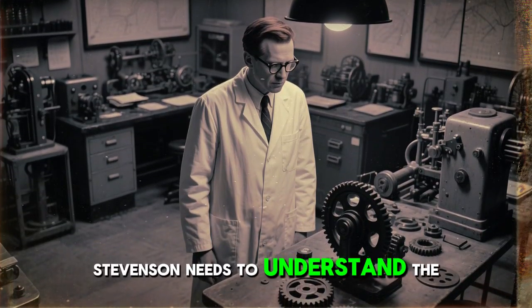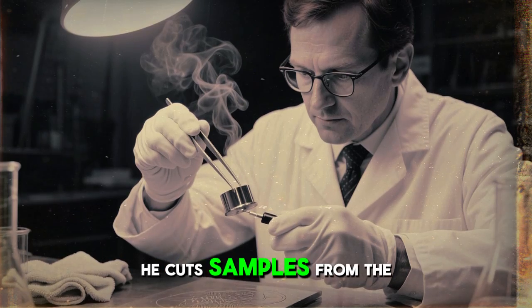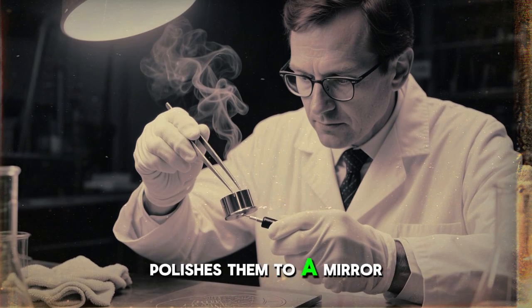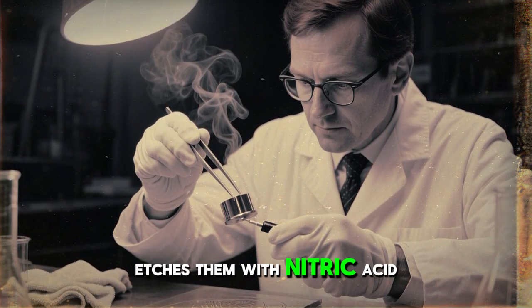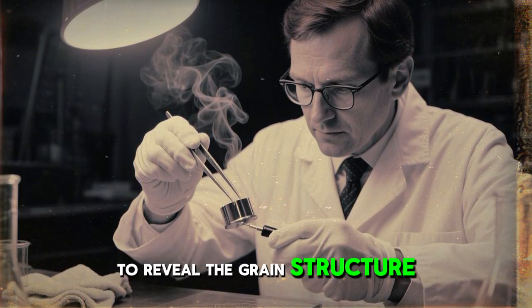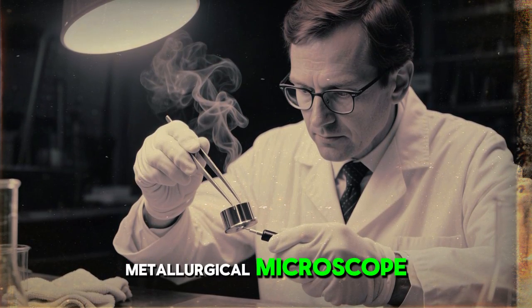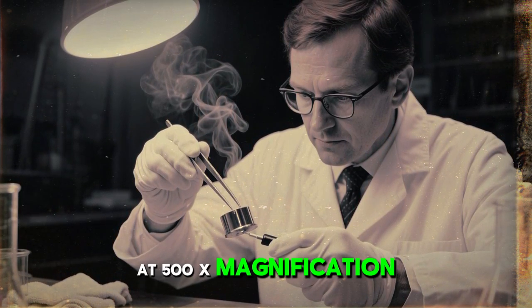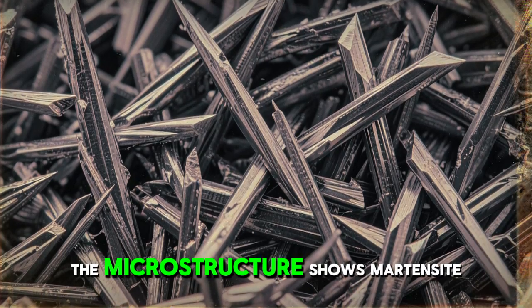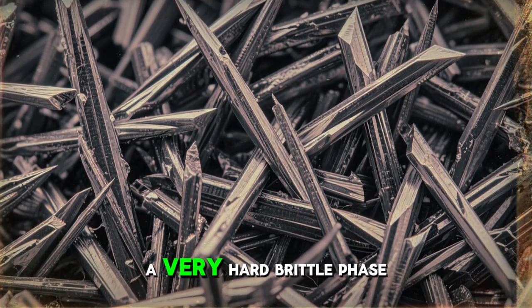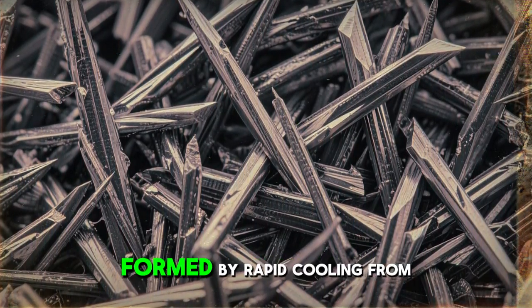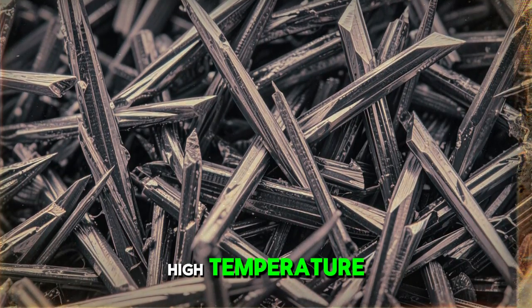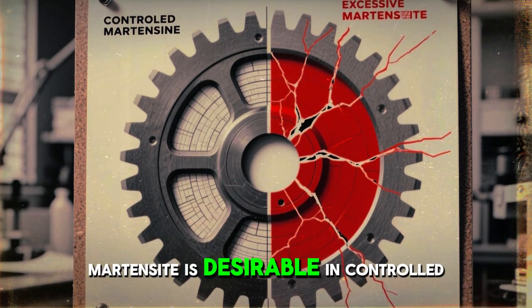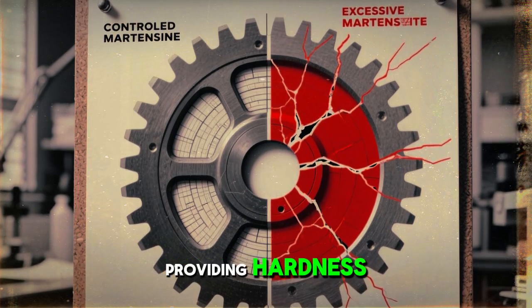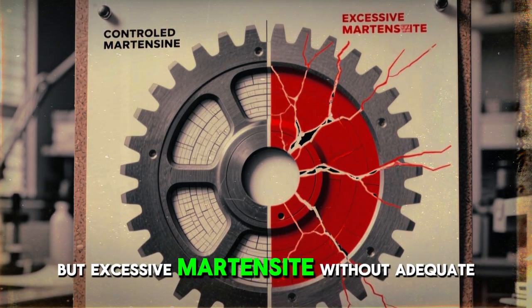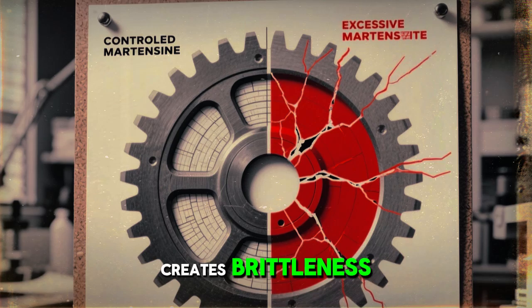Stevenson needs to understand the microstructure. He cuts samples from the gear, polishes them to a mirror finish, etches them with nitric acid to reveal the grain structure, and examines them under a metallurgical microscope at 500x magnification. The microstructure shows martensite, a very hard, brittle phase of steel formed by rapid cooling from high temperature. Martensite is desirable in controlled amounts, providing hardness, but excessive martensite without adequate tempering creates brittleness.